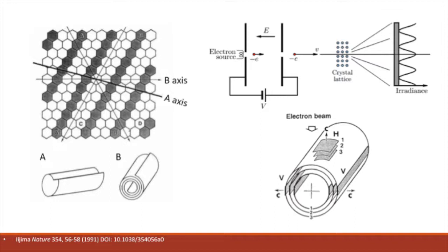Since all of the nanotubes were multi-walled, Dr. Iijima simply counted the number of diffraction patterns that were produced by each sample. If the number was odd, then he knew that his sample was in the end-to-end orientation. But if the number was even, then he knew that his sample was in the staggered position. Vast numbers of nanotubes were analyzed, and the primary consensus was that most of the tubes were in the staggered orientation.